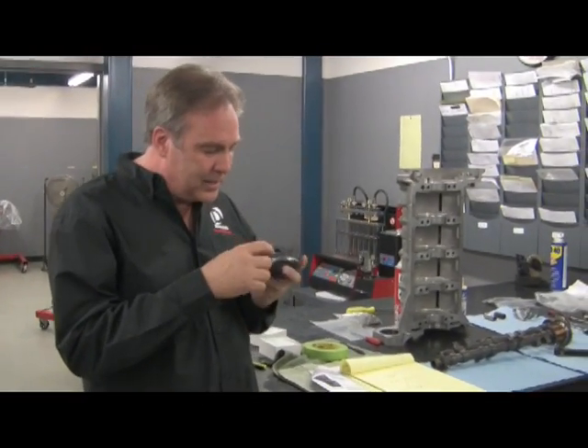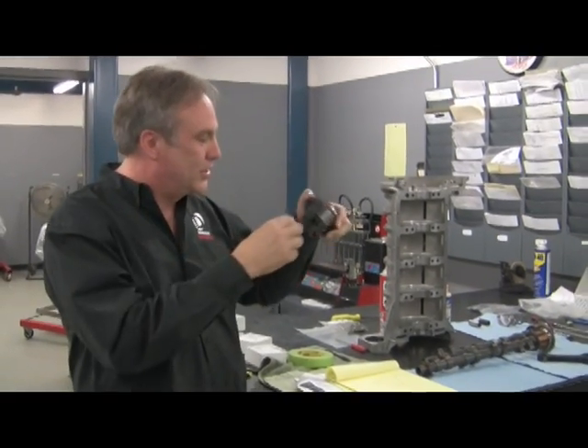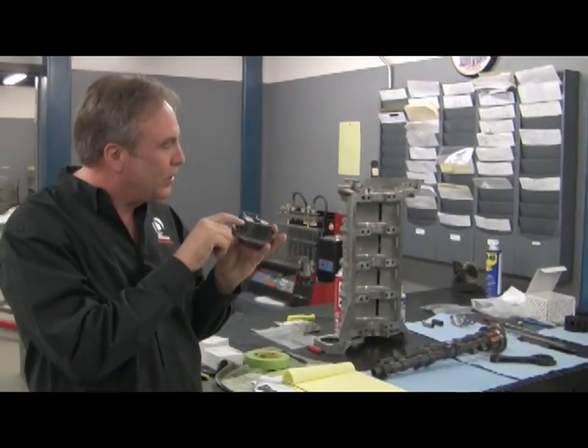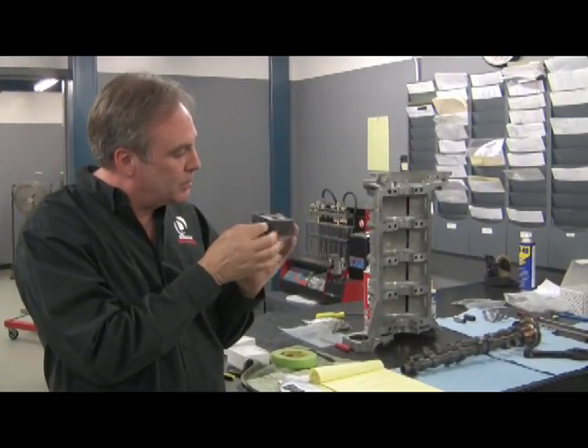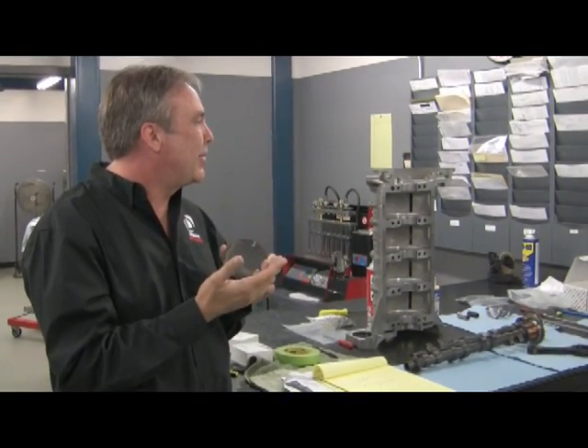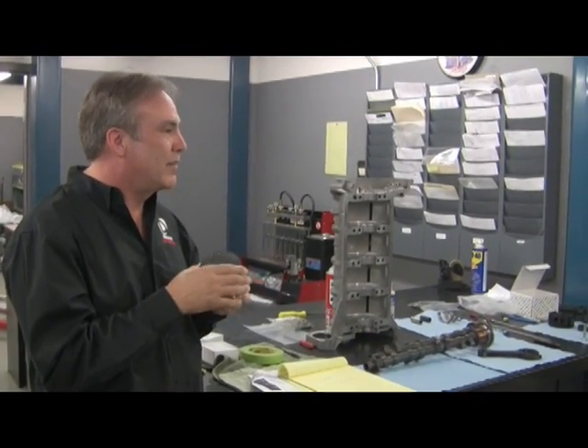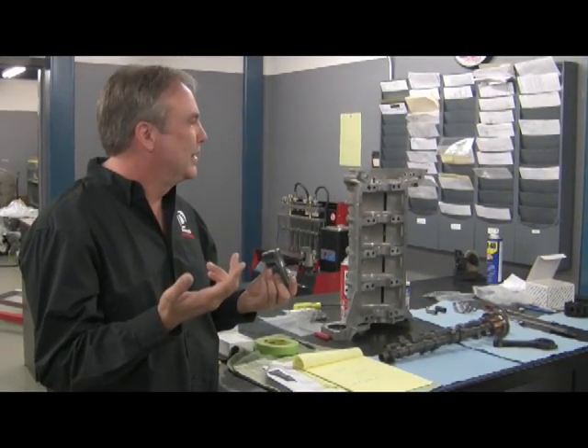For example, on the V10, the load was so high that the wrist pin would oval. So when the cylinder fires, it actually ovaled the pin. Temporary deflection, yeah. It didn't permanently flex back, but it left 4 little contact marks inside the pin bore. And ultimately that spreads the pin bore so you get a crack, and the crack will migrate to the piston crown. We've had that happen in race engines before. And then you wind up with a catastrophic failure, but it doesn't happen until 40 or 50,000 miles down the road. The only way to catch that kind of stuff is you literally saw the piston in half, put it under a microscope, and look at all the bits.